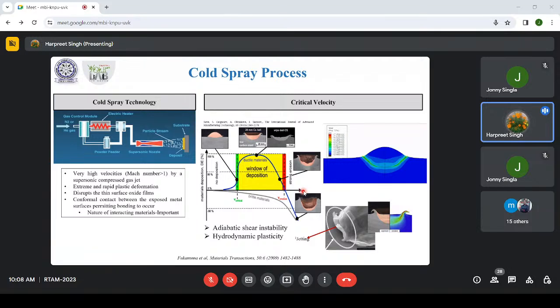deposition. So as an engineer, we can always define a window of deposition, and the point to be remembered here is that this window of deposition changes as you change the combination of materials. When I say combination of materials, I mean the substrate and the particle. Two materials are there: one is the feedstock material, another is the substrate. As soon as this combination is changed, the deposition process will change. In fact, this is something we have to do whenever we want to cold spray certain materials. Some effort goes into bringing the parameters to this level, to achieve this critical velocity and window of deposition, right?